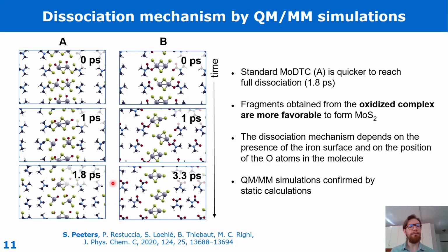On the left, you can see, for example, that the standard molecule has central units that are not very well defined. The oxygen is in the middle, and also sulfur atoms are close to molybdenum, which is a different fragmentation pattern from the one predicted by static simulations. On the right, we have oxidized MoDTC, where the central units have the correct stoichiometry to form MoS2, because the oxygen atoms have been pulled by the ligand units. And this is a very favorable situation to build the beneficial MoS2 tribofilm.